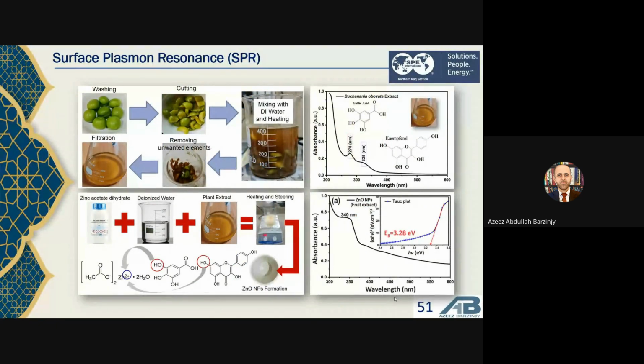And this is another case, for oxide nanoparticles. Here we use the extract of the plant, and then we produce the nanoparticle. But one thing is very important: before using the plant extract, you have to test it to see whether it contains a suitable phytochemical or not. In this case, we have two different phytochemicals. The first one appeared at 278 nanometer, and the second one appeared at 325 nanometer, and each of them belongs to one of the phytochemicals. You can see each phytochemical contains many OH groups and CH groups, which are important for producing nanoparticles.